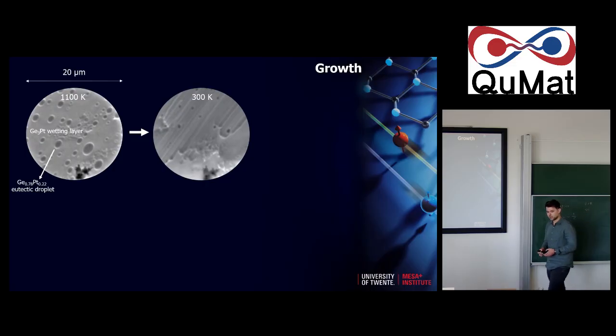So, okay, we took our 2D flakes again. We have a growth method that is quite controlled, and we can make them. It's a little bit of a complex process, but it involves eutectic liquids. Essentially, we deposit a lot of platinum on top of germanium, a few monolayers. We heat up to a temperature where you have a eutectic composition that melts, and you form these droplets. This is a low energy electron microscopy image.